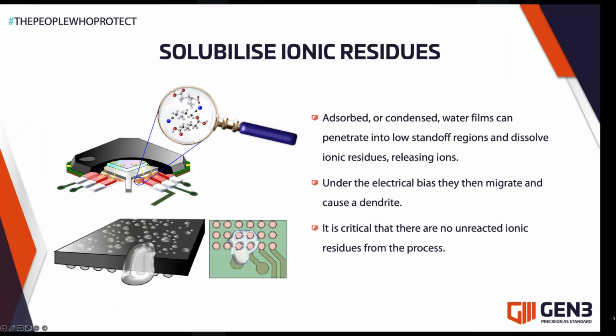So this is talking more about the issue of entrapment. So under the components, the flux residues could remain, or some ionic contamination, and they could be quite well bound in. It could be difficult to remove, or it can be difficult to test to see if they're there. But SIR testing will tell you whether that residue is harmful. By applying a bias on an SIR pattern underneath this component, we can see if there is any mobility, is there any charge flow, will there be any corrosion. So SIR is very useful in investigating this entrapped, potentially insoluble residue, which may create a problem in the future.